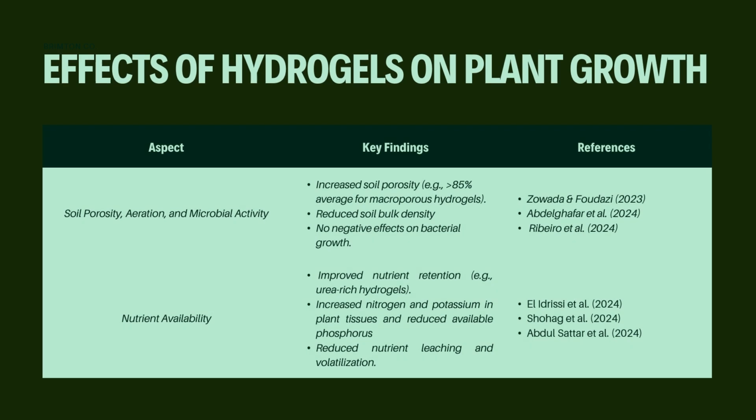Regarding soil porosity, aeration, and microbial activity, Zowada and Foudazi in 2023 found an increase in soil porosity when using macroporous hydrogels. Also, Abdel Ghaffar in 2024 found a reduction in soil bulk density. Ribeiro in 2024 found that there are no negative effects on bacterial growth.